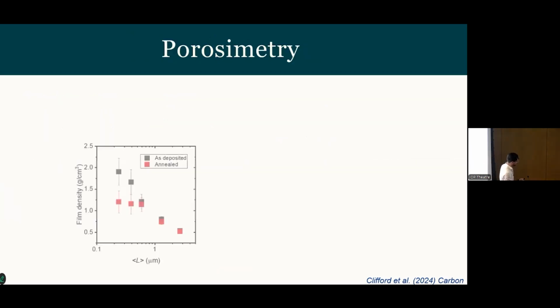The samples are big enough that we can weigh them and do macroscopic porosimetry. We can measure the density before and after annealing the surfactant out and work out the full volume fraction composition of the samples. And we find that the smallest samples are more conductive, even though they have all this excess surfactant. So the takeaway there is that the surfactant is what helps us exfoliate the materials and change the mechanical rigidity. And when we change the mechanical rigidity, we change the junction resistance. We start to recover improved transport in these films that we expect for the materials.